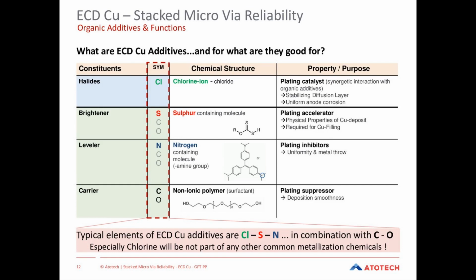We have then a brightener in the solution. This brightener is also called accelerator, and it is usually a kind of sulfur-containing molecule. We have a leveler containing nitrogen as a part of the amine groups in the leveler, and we have a carrier, which is usually a non-ionic polymer. This overview should give you an idea now what elements you have to expect on the interface of stacked microvias when the nucleation of the electroplating copper process starts.